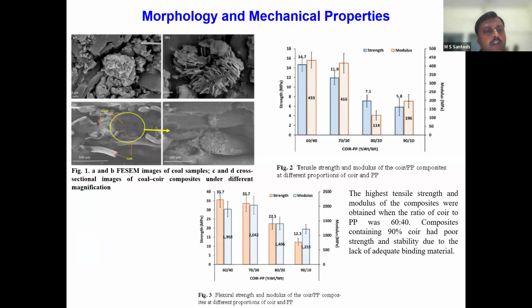In terms of the morphology, when you look at the microscopic graphs, it clearly indicates that there is a bit of aggregation of these coal samples at some point in the material in figure A that you can see. And in figure B, there are sheet-like morphologies that are visible, which are clustered together in one portion of the image. But figures C and D clearly indicate how these coal coir composites can be visualized.